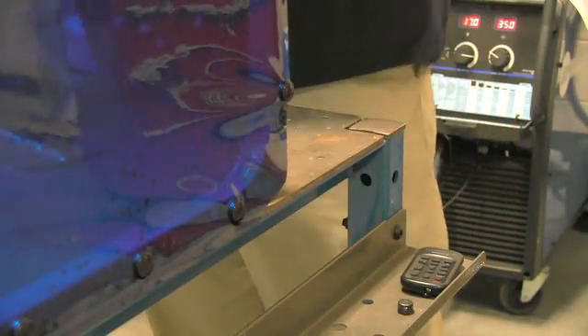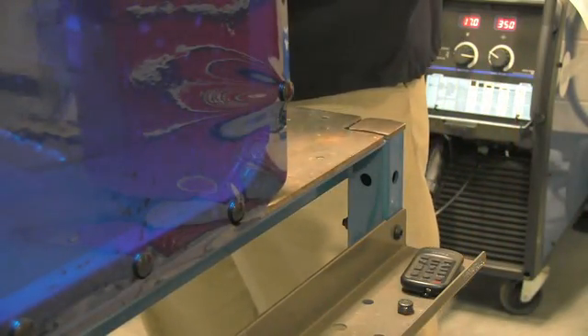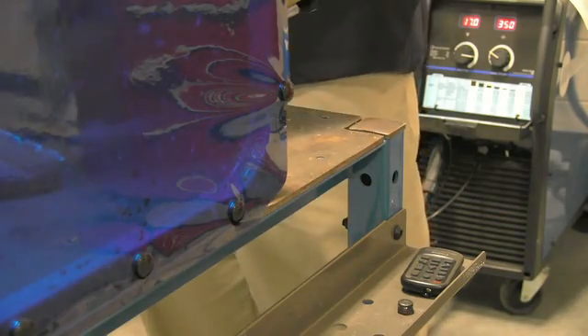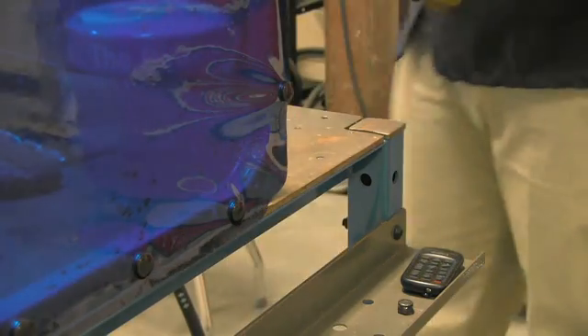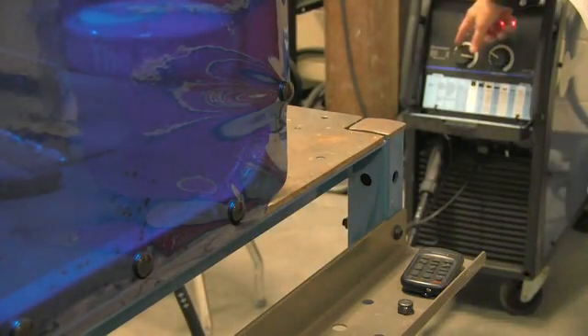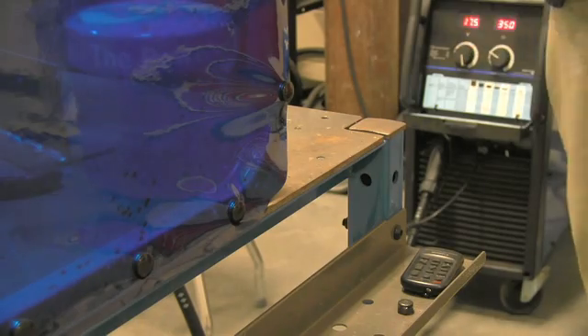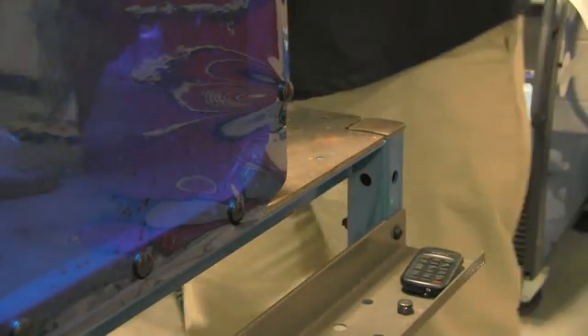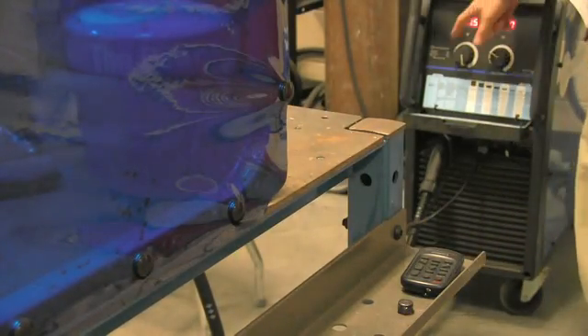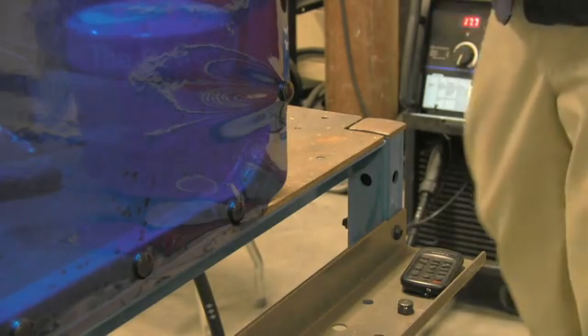Okay, that was a little bit better. We were able to get a nice start, but there's still a considerable amount of spatter being generated and it still sounded a little unstable. So now from this point I'm going to go up just a half of a volt at a time until I get that really nice stable short circuit sound that we talked about. Right there is pretty close, sounded like bacon frying, but I still think we need just a little bit more voltage. I'm going to go up 0.2 volts.